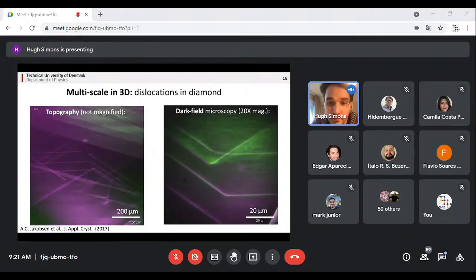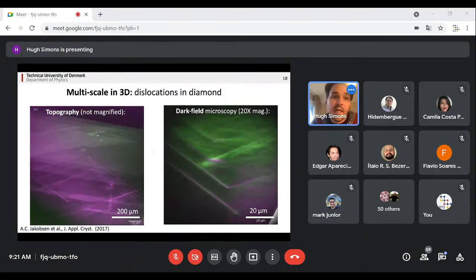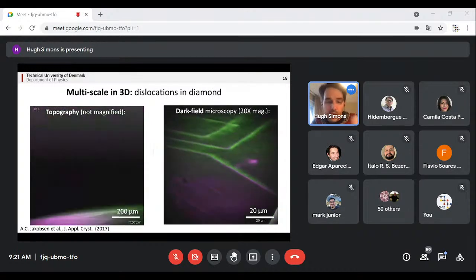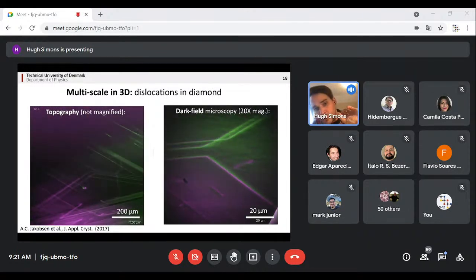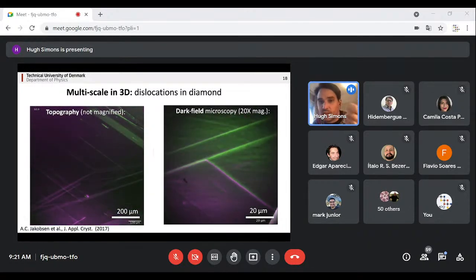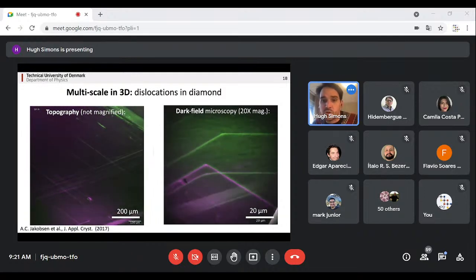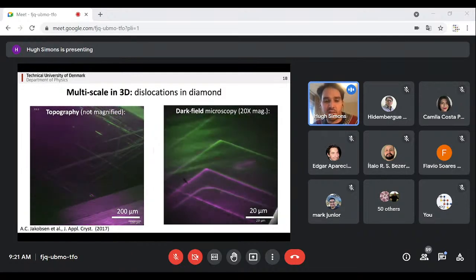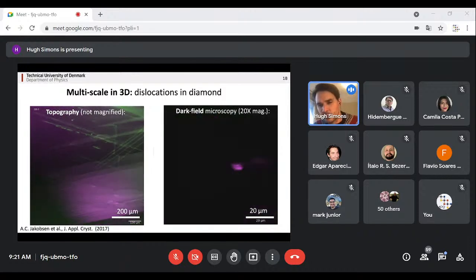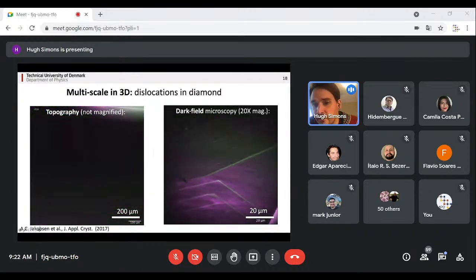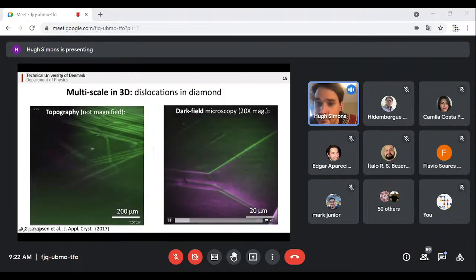And we happened to have this piece of artificial diamond. And using a slightly different experimental configuration, we were able to rotate the sample whilst maintaining the Bragg condition. And this allowed us to collect data in this so-called topotomography mode, which is a lot like a tomographic 3D scan.